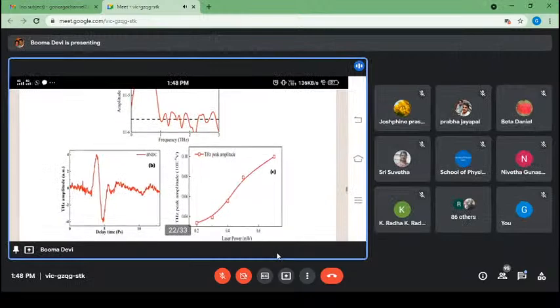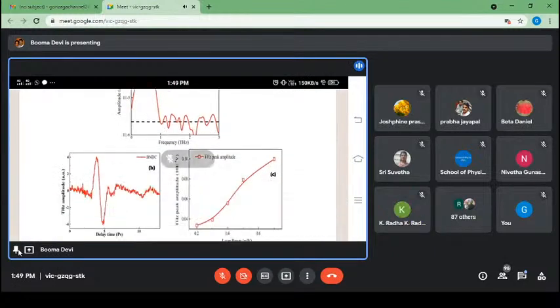Here you can see the generated frequency range. It is good between 0 and 1.2. It shows broad transparency for terahertz waves. Then you have smaller, minor absorptions due to the nature of the BNDC molecule. This transparency range, in which BNDC shows good transparency, could be used for explosive detection. Most explosives have absorption between 0.1 and 3 terahertz, so this molecule could be used for detection of explosives.